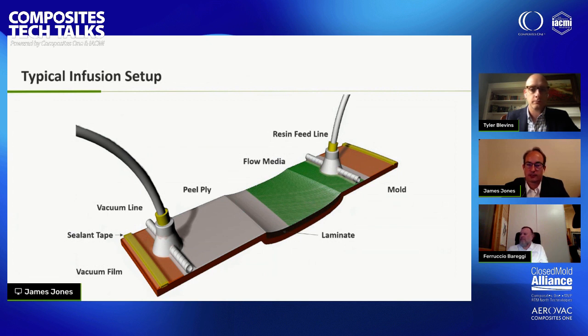So the reinforcements commonly used in wind blades are non-crimp unidirectional multi-axial fiberglass or even carbon fiber. As I mentioned, core materials are either end grain balsa wood or polymer foam. So in infusion, these are all loaded into the mold dry. So there's no resin. There might be some contact adhesives to hold everything into place while we place all the processed materials in the vacuum bag.